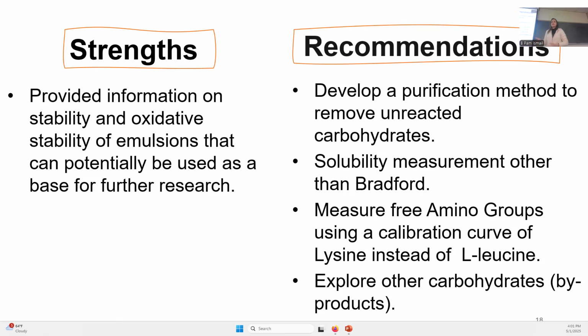For the solubility measurement, they used Bradford, but they could have measured the protein content in the supernatant by Kjeldahl or Dumas or another more reliable method, and increased the concentration. Also, to measure the free amine groups, like I mentioned before, they used L-leucine as the calibration curve, and we know that lysine is the amino acid that is more reactive in the Maillard reaction, so they should have used a calibration curve with lysine instead of leucine.